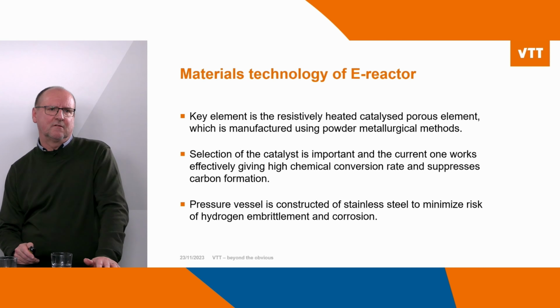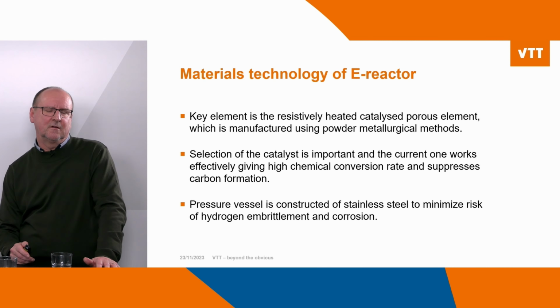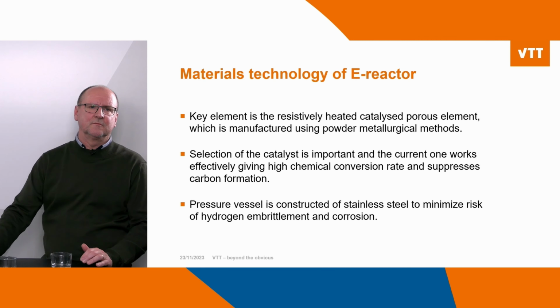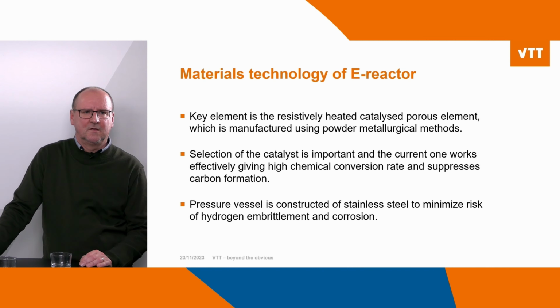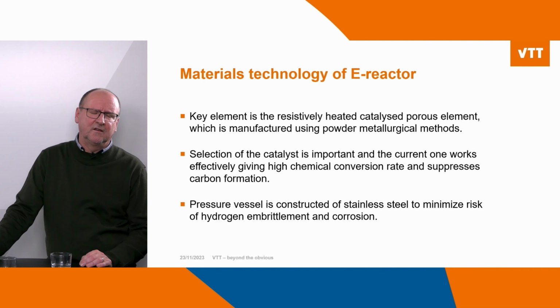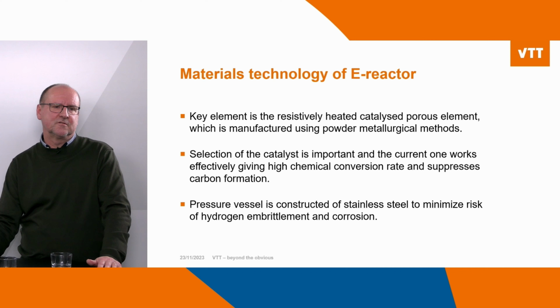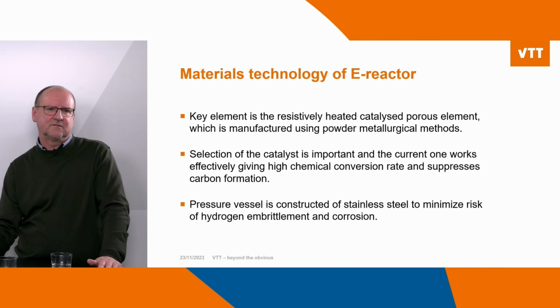So still summarizing the material technology side very shortly. We have the catalyzed heated porous element, which can be manufactured, for example, using powder metallurgical methods. And this catalyst selection is very important, so that reactions happen as they should. But what we have found in our case is that this reactor type suppresses the carbon formation on the surface of this reactor. That's a very positive thing, of course.